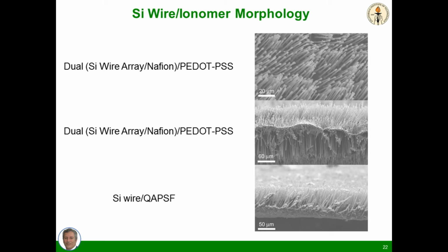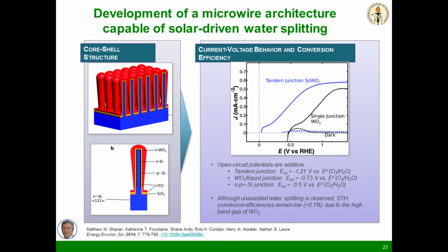To demonstrate that this worked, we took the microwire array and made a conformal self-aligned structure by abandoning the top and bottom just for expediency purposes, and deposited by vapor deposition or other methods a layer of tungsten oxide as our second absorber on top of the silicon. That's our blue light absorber, and the silicon's our red light absorber. By depositing it conformally in this way, we don't need that pesky little conducting polymer intermediate plane, because the electrons on every wire have a clear shot to go from the top of the membrane to the bottom of the membrane. Tungsten oxide is also one of the few metal oxides that's stable in acid, and it was compatible with the silicon stability in acid and the membrane stability in acid.